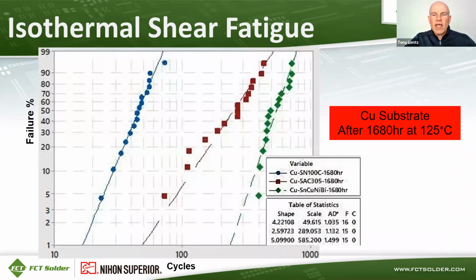And then after aging 1680 hours at 125 C, you can see that these curves have moved around. The red squares for Sac-305 now have a shorter life than the tin, copper, nickel, bismuth, which is the green diamonds. And so that just shows again that Sac-305 loses its effectiveness, its strength over time.